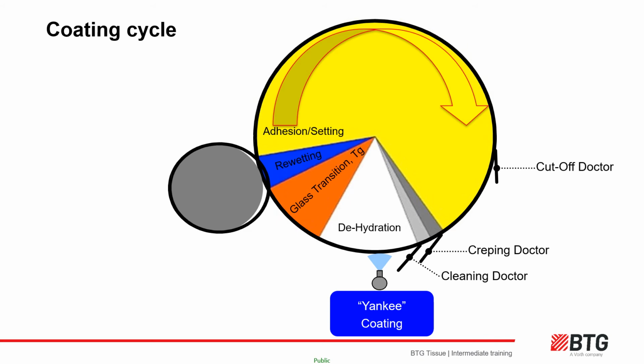The cut-off doctor will be raised at this point, and at the creping blade the sheet is creped off the cylinder, the blade sitting through the sheet partway in the set and flexible coating film. The release oil added to the coating mix by this time will have migrated to the sheet and coating interface to help the sheet release from the Yankee and build stretch.